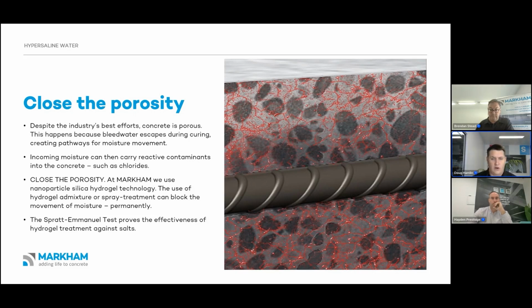Such as chlorides in a marine or hypersaline environment. There could be many other contaminants that get carried into the concrete and move through these porosities, transported by the moisture. So it's really important when you're talking about concrete service life to close that porosity or seal it up, and that's where we at MARKHAM come in. Our technology, the hydrogels and the colloidal silica particles, work to seal that porosity up. They form a gel inside those pathways and stop that moisture transmission from the surface of the concrete down into the matrix.